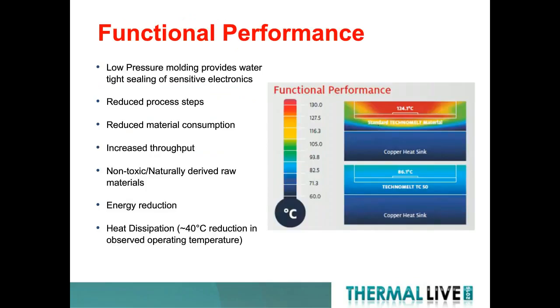This is a thermal model developed internally here at Henkel, where we looked at unfilled material at 0.2 to 0.25 watt per meter-K versus filled material at 0.5 watt per meter-K. What we did is try to develop a part that we could use to test the actual difference between these two materials in terms of functional performance and measure its actual benefit for an application itself.